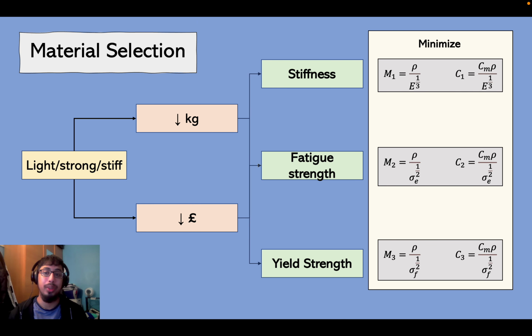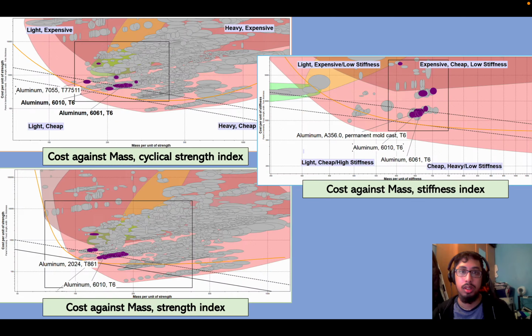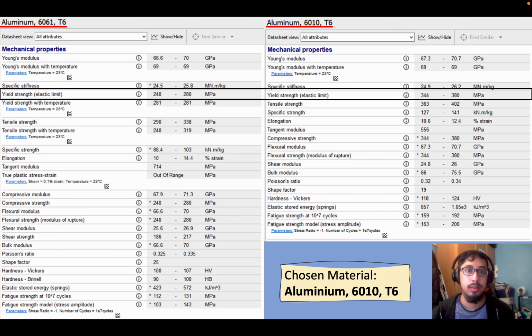For each of our constraints, we used material indices to minimize the mass and the cost. These two conflicting objectives were plotted against each other for every constraint. The penalty function was thus created with an alpha value of 1, valuing both cost and mass equally. The most viable materials were on the lower left quadrant, closest to the penalty functions. Aluminium alloys and magnesium alloys were the most viable, but we boxed out magnesium for their inferior corrosion resistance. Of the aluminium alloys, the two best were 6010 and 6061, but we opted for the former due to its superior yield strength.